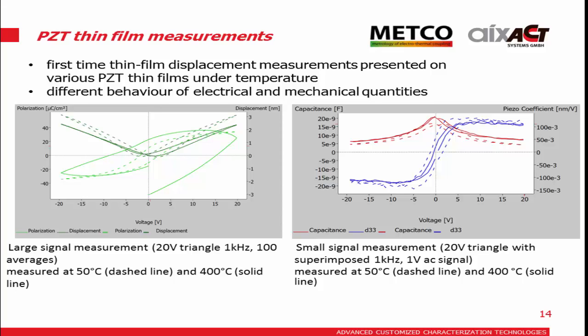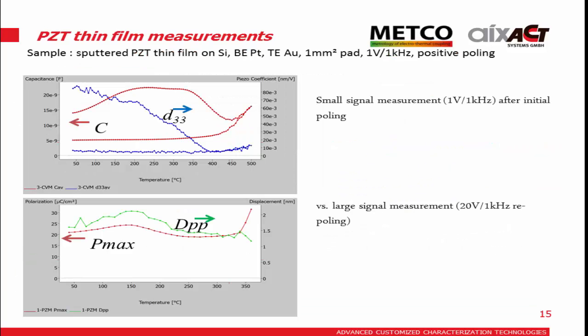Some of the work we've done on bulk soft PZT, and I would imagine the same thing would happen on hard PZT, is that you still see piezoelectric activity significantly above the Curie temperature for high fields, and because this is biased, it essentially becomes electrostrictive. You can see if you had 0 volt, there would almost be no D33 left, only if you excite it at a high field. And this is something we see with the bulk as well. So this is a different material.